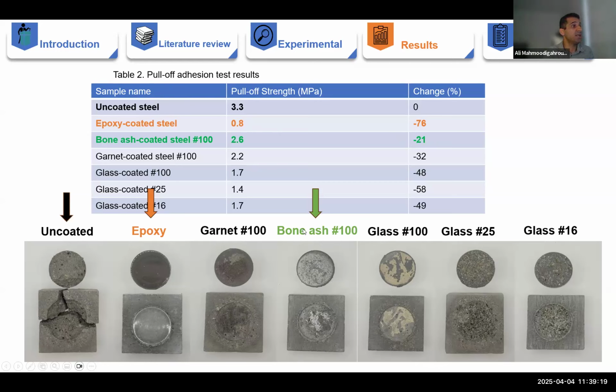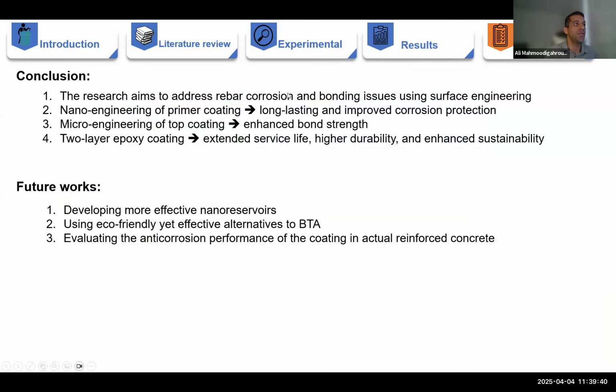And like I mentioned earlier, this is because when we add abrasive material on the surface, we improve the bonding both physically and chemically because we change the surface chemistry and we introduce texture on the surface. In general, the research aims to address rebar corrosion and bond issues using surface engineering. Nano engineering of primer coat provided long-lasting and improved corrosion protection. Microengineering of top coating enhanced bond strength. And in general, two-layer epoxy coating can provide extended service life, higher durability, and enhanced sustainability.